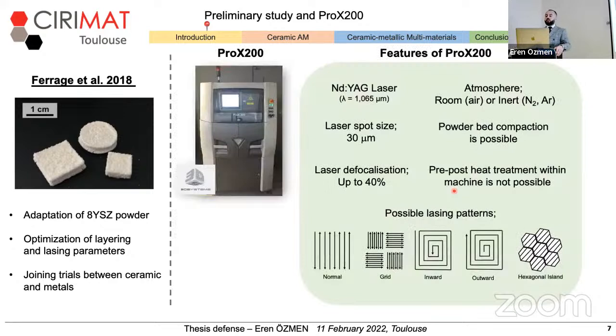Pro X200 from 3D Systems was used as the PBSLP machine, and this machine is equipped with an Nd:YAG laser, which has a spot size of 30 micron. And this spot size can be adjusted up to 40% by the defocalization option. This PBSLP machine allows users to perform their studies in air or room atmosphere or inert atmosphere. Powder bed compaction is possible with the help of a roller drum in this process, and pre and post heat treatment within the machine is not possible.